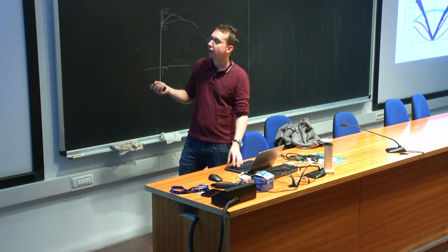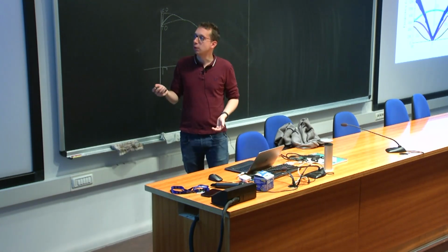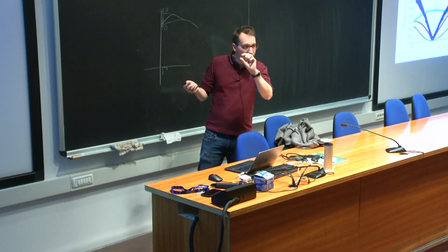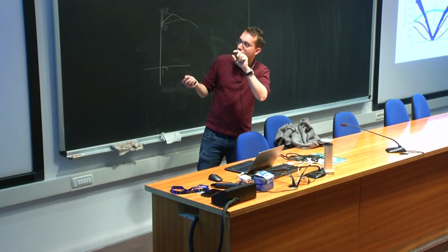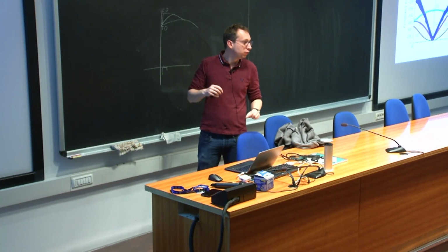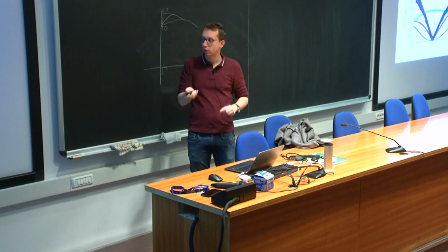And so once you have this ingredient, you put them in, and you can compute the line width of the phonon. Here I put the phonon dispersion of graphene, and the colored band around is the line width of the phonon multiplied by a factor 100. Graphene is very harmonic, so the phonons are actually a very narrow line.